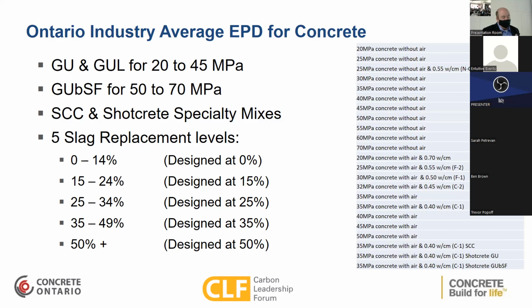So for example, I'm showing here in Ontario, we came up with the 22 most used concrete mix designs. So we went through, surveyed our members, found out what are people actually using on projects, because we want to try and capture as much as possible. If we're going to tackle the carbon challenge, we need to identify where the high volume applications are. We need to optimize those as soon and as quickly as possible. So what we've done in this basic breakdown is identify the different mixes that we're going to use.